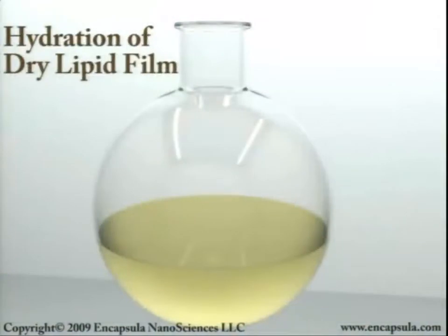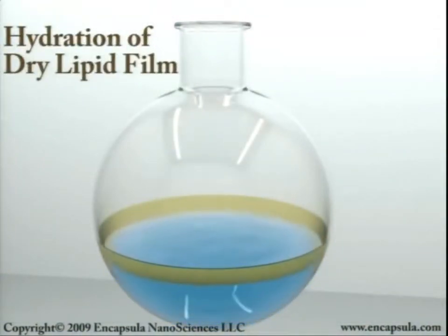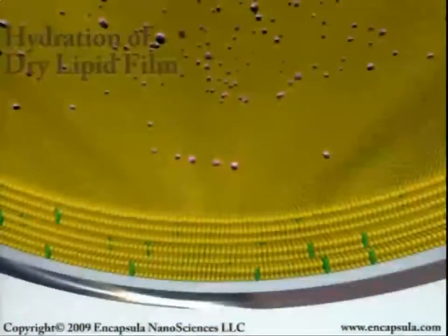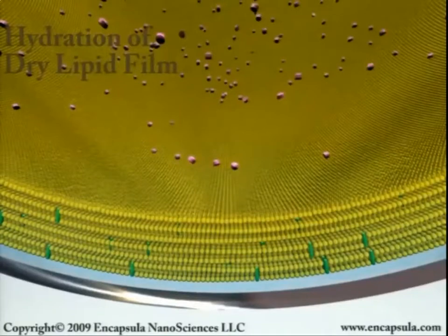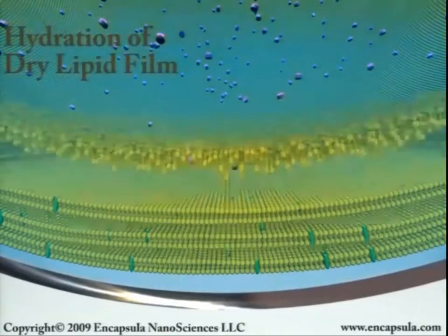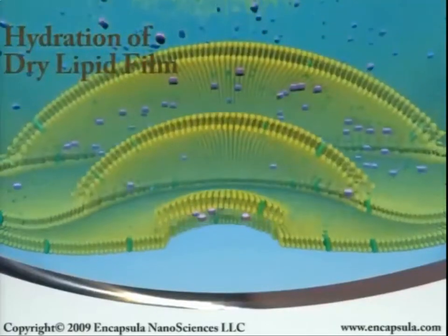Some solvents can be removed by lyophilization, resulting in a dried lipid cake. An aqueous solution containing water-soluble compounds to be encapsulated is then added to the lipid film or cake to hydrate the lipid and form the liposomes. The aqueous suspension must be heated above the phase transition of the lipids in order for the liposomes to form. The resulting multilamellar liposomes consist of many concentric lipid bilayers.